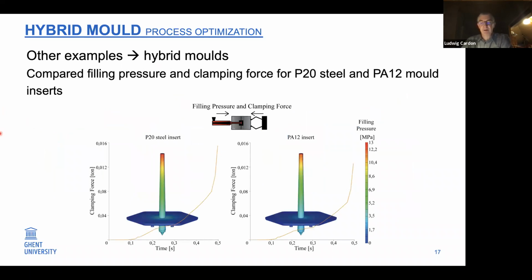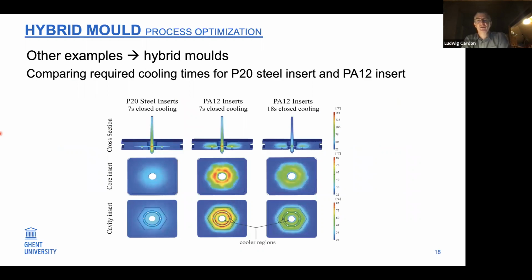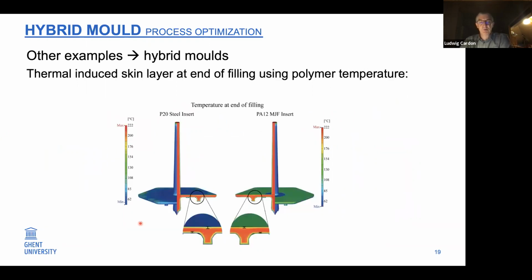Okay, I will pass by these slides, but this one I showed you already in the overview, but more important for you to explain will be this one. When you have the P20 steel, a standard steel mold, you can identify inside the flow simulation the so-called skin layer. What does this mean? The top and bottom of your mold cool down. When it's steel, this will cool down very fast and becomes, let's say, blue. But the inside, which has contact with the mold and creates your skin layer, will cool down somewhat slower. So when you inject polypropylene material, the crystallinity in the middle will be higher compared with your skin layer, which is a more amorphous structure.